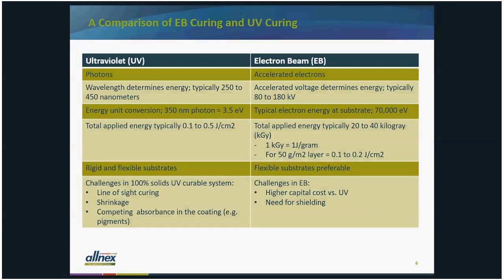So we start to look at comparisons between UV and EB. Again, ultraviolet cure uses photons, electron beam uses accelerated electrons. With UV, the energy is determined by the wavelength of the energy that you're using, whereas with electron beam, the energy of the electrons is determined by the accelerated voltage in the EB equipment. Typically somewhere 80 to 180 kilovolts, maybe a little higher.